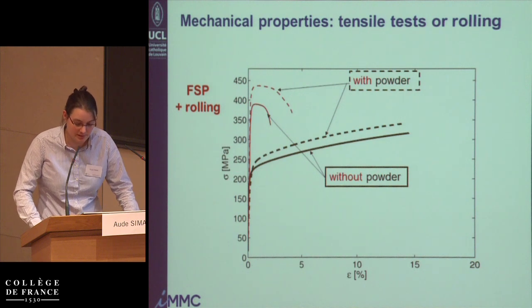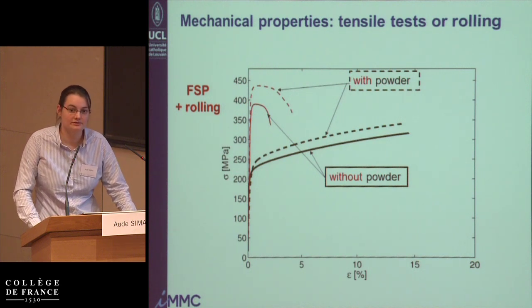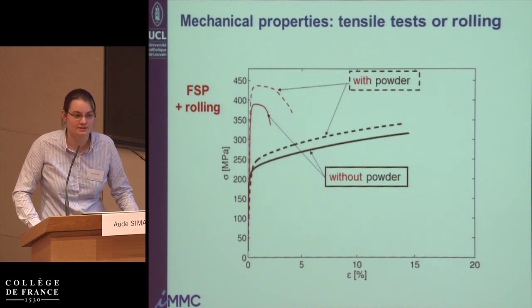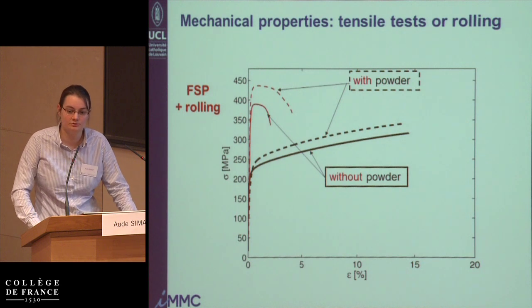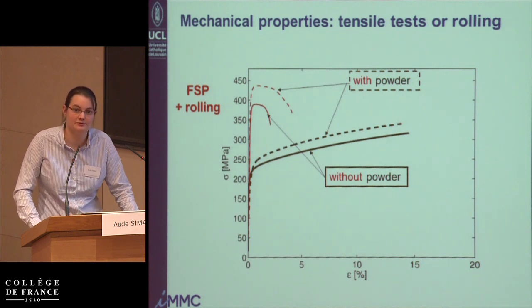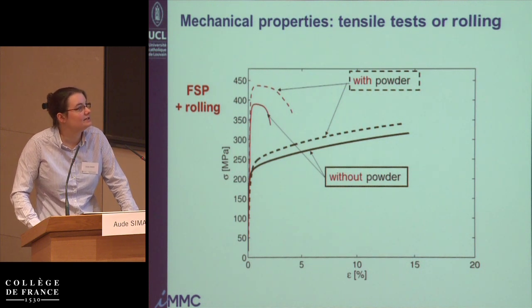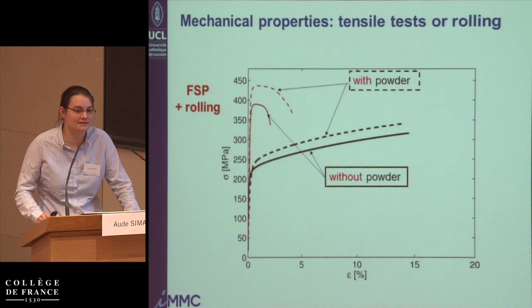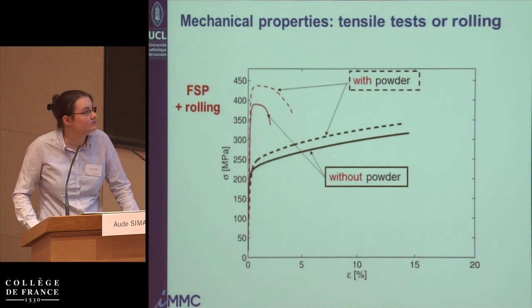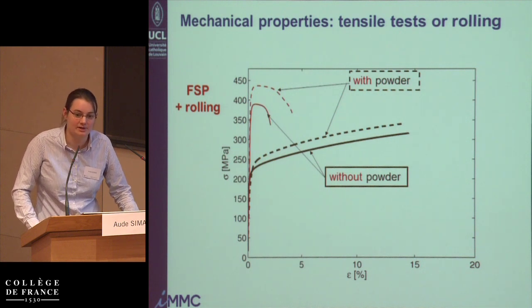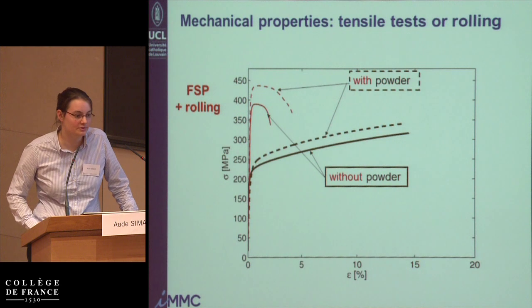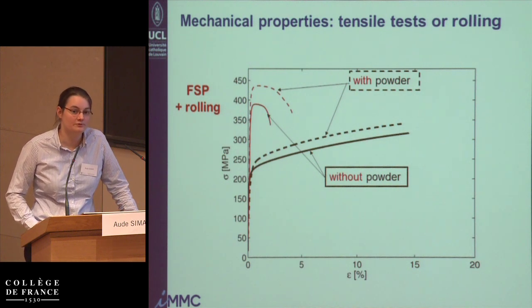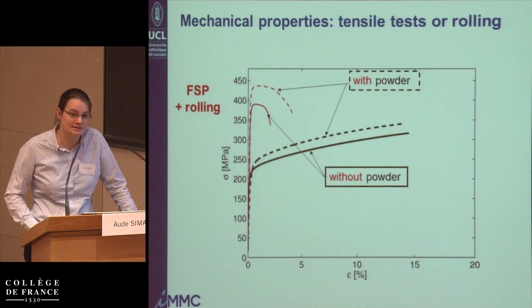And I've told you about the rolling that we did of these materials. We thought that if the strain hardening ability of the material is really good, it might be interesting to push it harder and go to 75% of deformation by rolling. And doing that, well, we have about 50 megapascal difference in yield strength between the material without powder and with powder. So we're actually improving the properties of this material after rolling. Well, of course, it gets very little ductile, and so we probably need to improve the choice that we make here in terms of rolling levels.